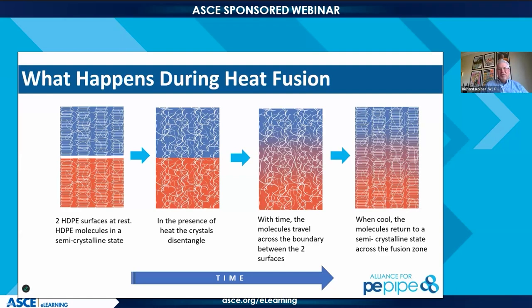Yeah, Doug, you described it beautifully. But really what this means is we become monolithic. So I know Doug mentioned a joint, but it's really not a joint. It becomes now part of that same structure. So that's why we find the fusion process and the area of the interface where these molecules come together and combine actually provide a stronger element. And in my opinion, it's because that process is fairly slow in cooling. And so like a pipe, when we rapidly cool it and pull that heat out of there, we can affect how that crystallization forms. But when it slowly cools through the fusion procedure, it actually becomes a little bit more dense. So it becomes stronger than the parent pipe.